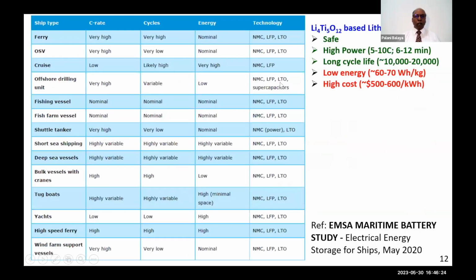I'm skipping some of this slide, but I want to emphasize that the marine industry goes through quite a lot of vibrations. Mechanical abuse is something which I skipped because there is not much time. So mechanical abuse in the marine industry is well known. You can see here almost all the applications use more or less lithium titanate technology. This is a nice report. So that explains that lithium titanate is a robust technology and it can address mechanical abuse from the safety point of view. But unfortunately, as you can see, it's too expensive, $500 to $600 per kilowatt hour. If you are comparing LFP versus graphite, it is somewhere in the range of $125 to $150 per kilowatt hour.